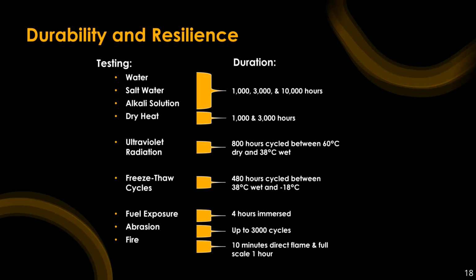And then I'll pick back up on the durability and resilience. This is one of the items that Habib touched on. That's one of the advantages of using FRP composites in civil infrastructure applications. One of the ways that we back that up is with testing, and so we've put the materials that we use in both the arch bridges that we have constructed, as well as these girder bridges, through a pretty intense test matrix. You can see examples here of the different environmental exposures and durations we've tested these materials to. It comes from the International Code Council Acceptance Criteria 125, which was originally developed for externally bonded column wraps for seismic retrofits. But the application here is really no different. It's FRP being exposed to the elements.